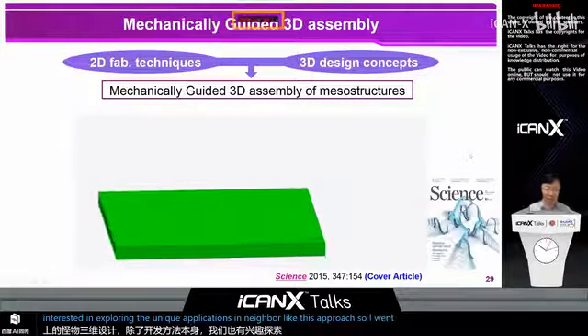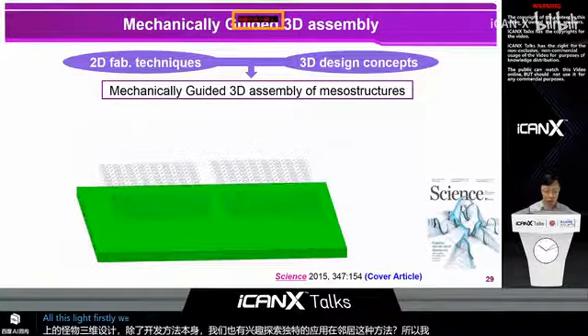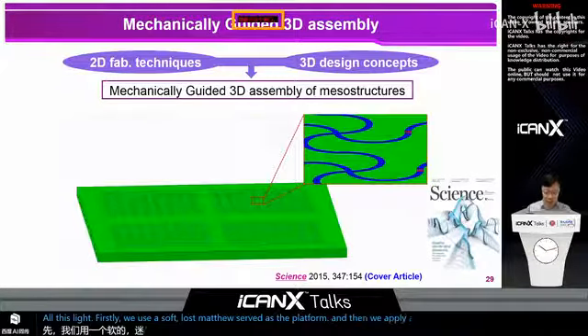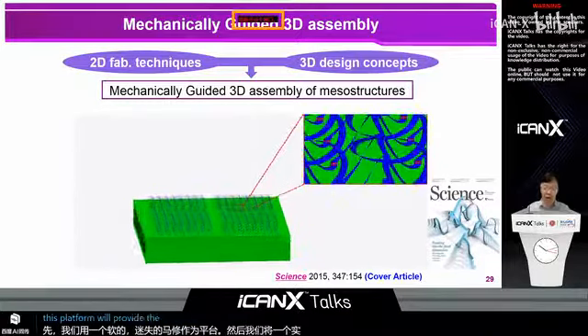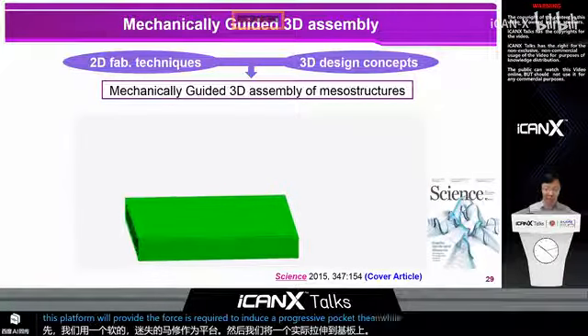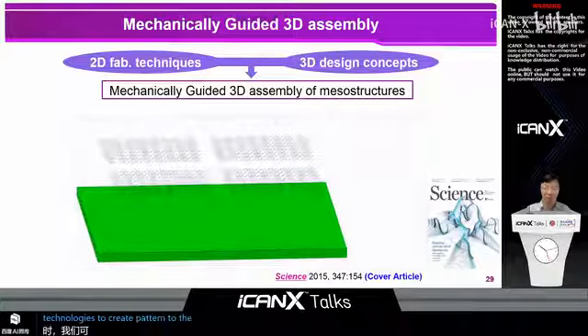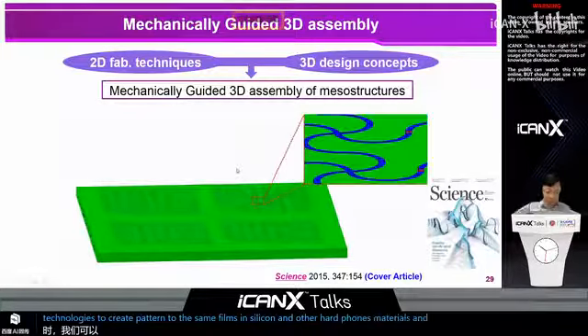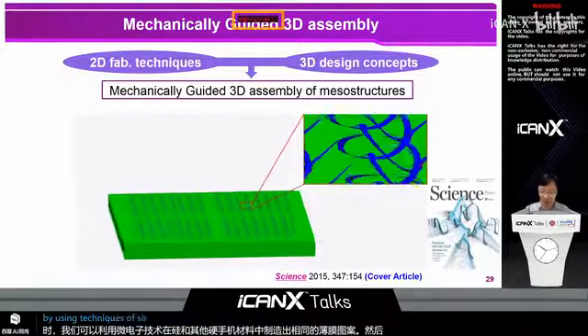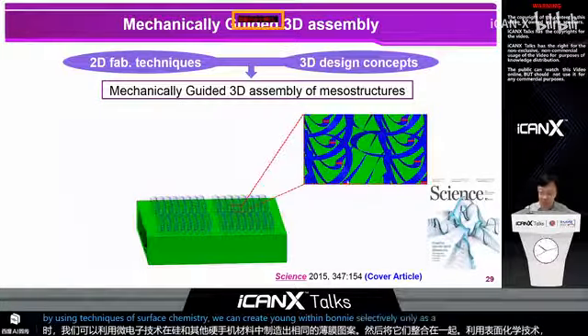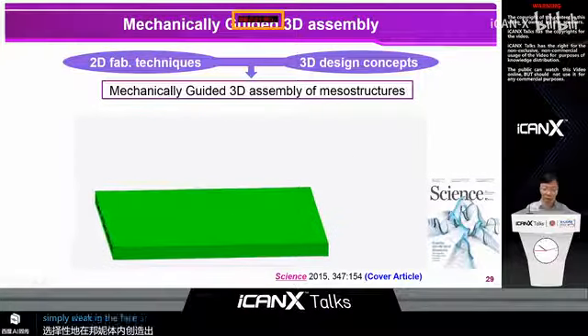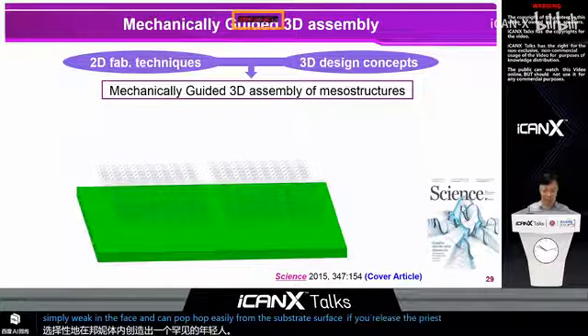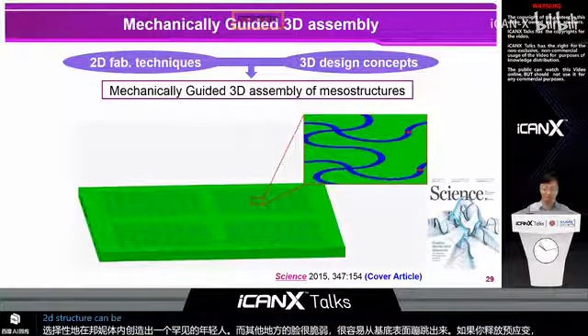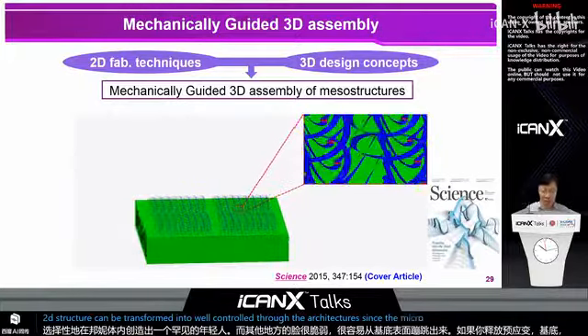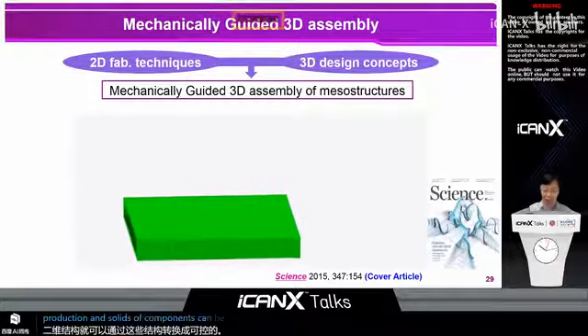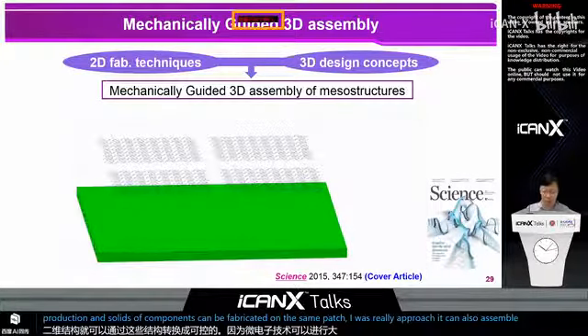So I will illustrate the process of this assembly on this slide. Firstly, we use a soft elastomer to serve as the platform, and we apply a biaxial pre-stretch to the substrate. And this platform will provide the forces required to induce the compressive buckling. Meanwhile, we can use the microelectronic technologies to create patterned 2D thin films in silicon and other high-performance materials, and then we integrate them together. And by using techniques of surface chemistry, we can create strong covalent bonding selectively only at the rest sites. The other places are simply weak interface and can pop up easily from the substrate surface if you release the pre-strain in the substrate. And then the 2D structure can be transformed into well-controlled 3D architectures. Since the microelectronic technologies can do mass production and thousands of components can be fabricated on the same batch, our 3D approach can also assemble thousands of 3D mesostructures at the same time.